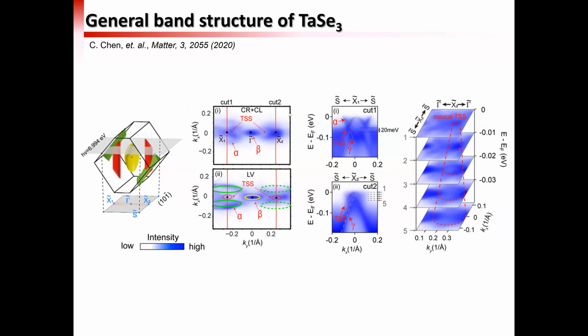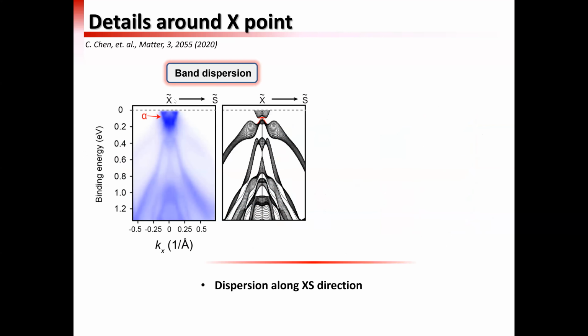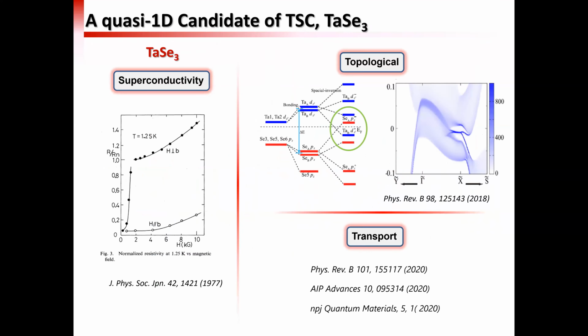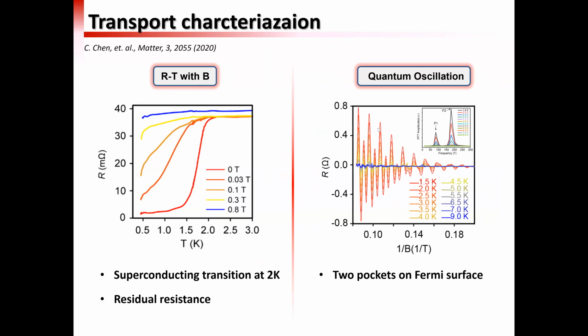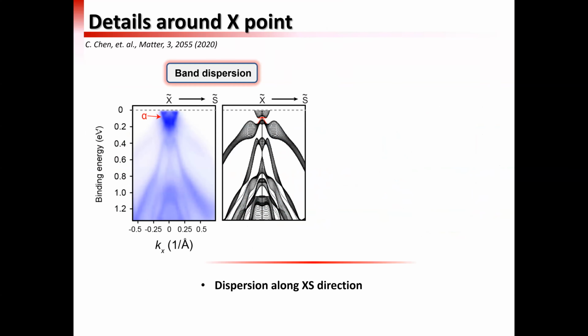So this topological surface state pocket and the 2 bulk state pockets make up the complicated quasi-1D Fermi surface of this material. Then if we zoom in to the X pocket, where our calculations show the band inversion happens, we can see in general it looks pretty similar to the calculation. There's the W shape conduction band pocket here, and you can see there are remnants of the two pockets here. The Fermi surface may not be exactly the same as in the calculation, and also the conduction or valence pocket is below.